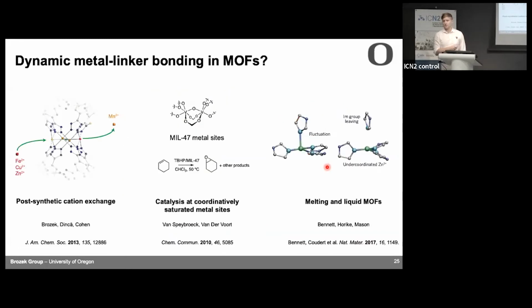Well, it's also important because it would help explain a lot of really important chemistry that we see in the MOF literature. So for example, if metal ligand bonds in MOFs are dynamic, this would help us understand how metal exchange happens. So there's this bizarre phenomenon that you may have tried in your own lab, where you take MOF crystals, you soak them in a different metal solution, and the metals switch places without destroying them, in a single crystal to single crystal transformation. So how does that even happen? And probably it requires these bonds to be dynamic.